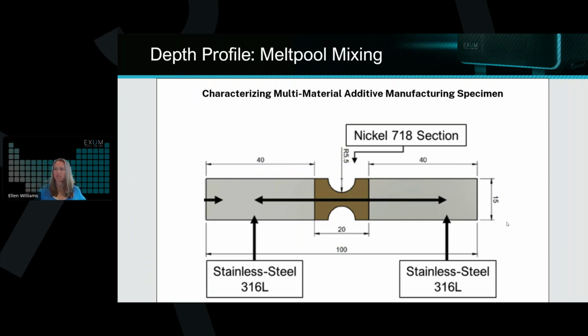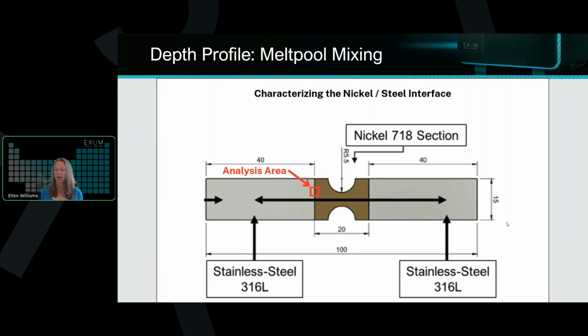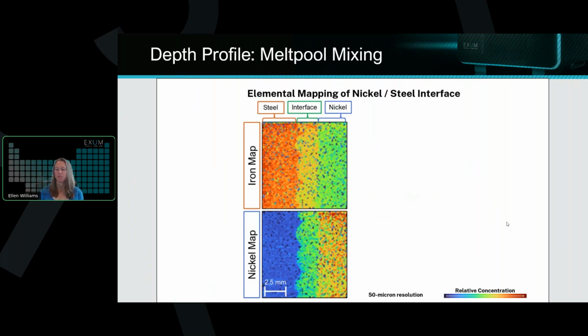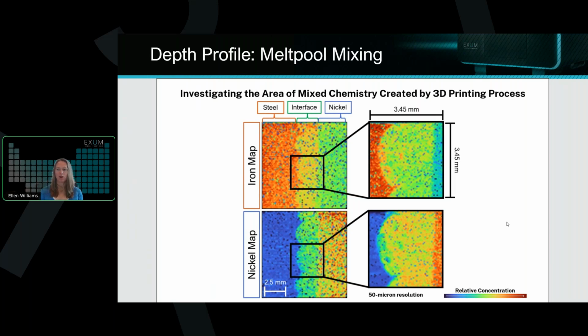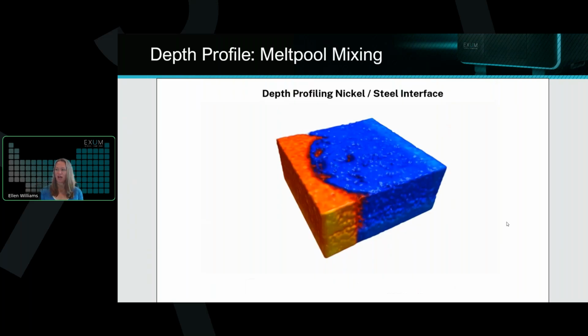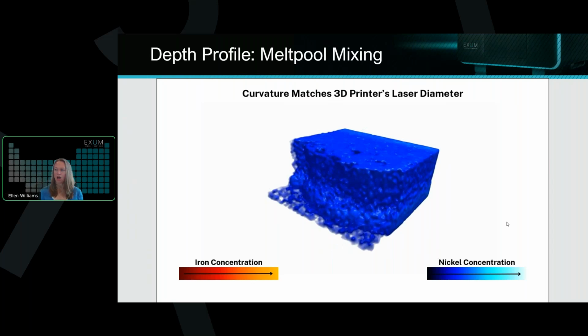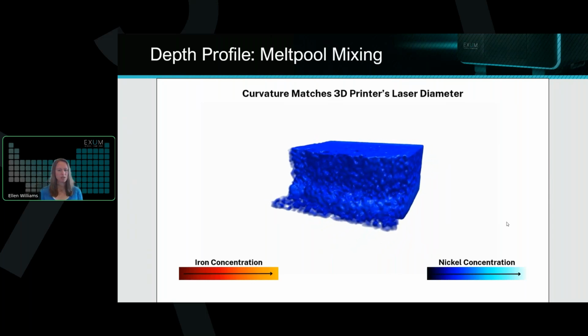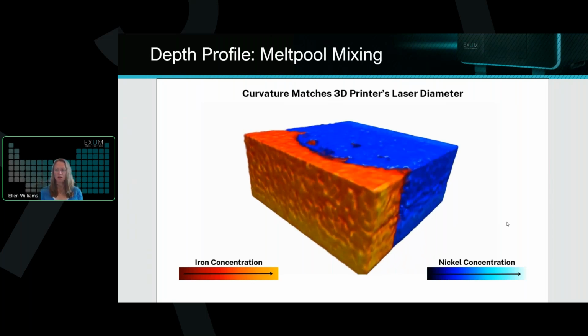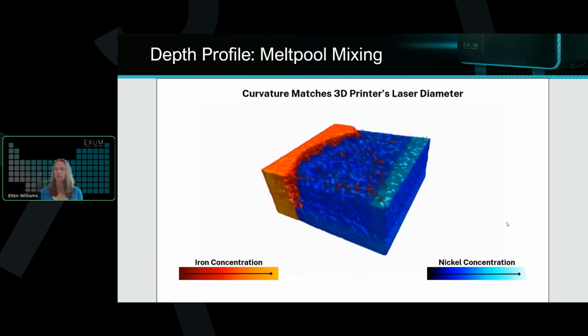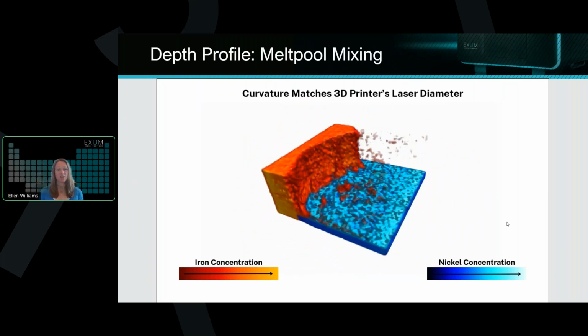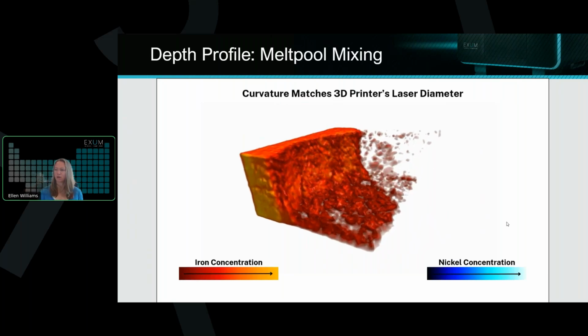And I think I'll just let this video play once more, just so you can see that once again, now that I've oriented you on the map. Doing that map, identifying where that interface layer is, and then doing a smaller area of 3.5 by 3.5, profiling through tens of microns of material. And of course, if we continued that process for a few more hours, then we could even get through a deeper amount of material. I believe the deepest depth profiles that we've done to date have been about 350 microns of material removed in order to see a specific feature and how that changes over hundreds of microns of material.